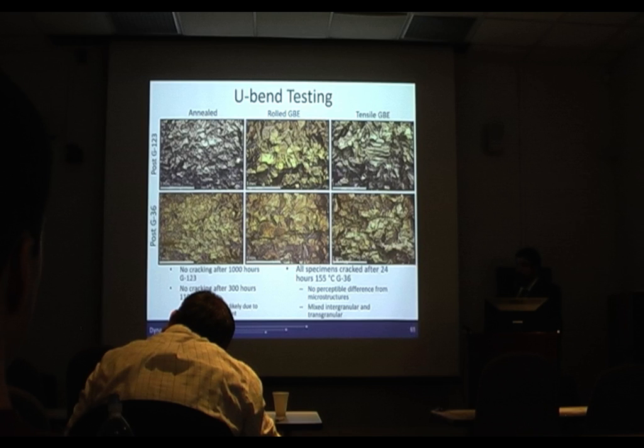Finally, we went for the full G36 at 155 Celsius, and within 24 hours, every single specimen cracked, and they appeared to be mixed mode intergranular and transgranular. So unfortunately, from that, we couldn't say much about how microstructure actually affects it because they all crack at the same time, appear the same, especially with transgranular cracking. However, an interesting note from that is that relatively modest nickel content in 316L massively increased the stress corrosion cracking resistance, which was not expected. So our conclusions.